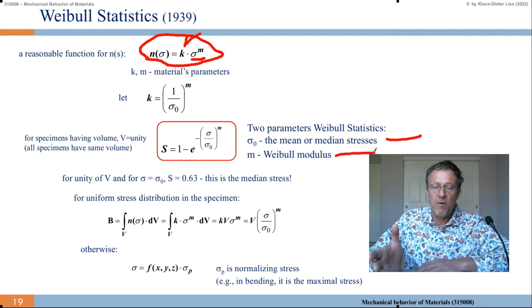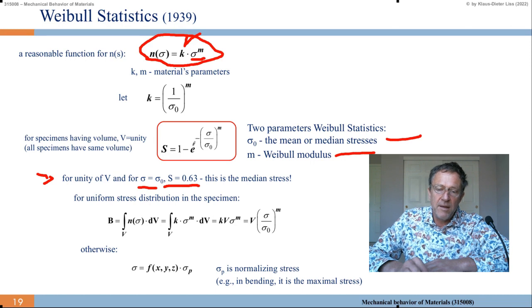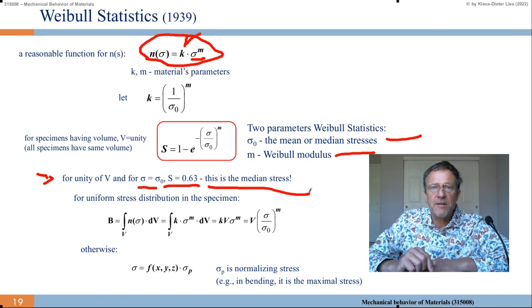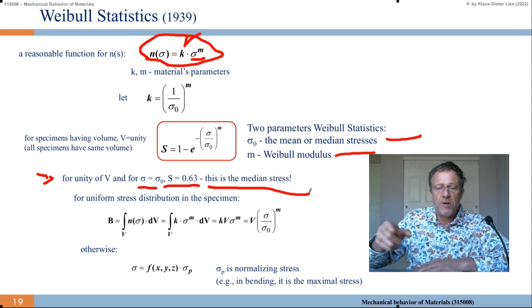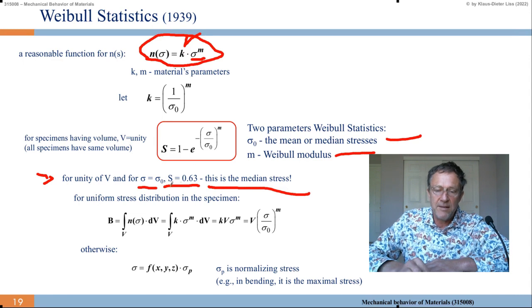We have seen that before, right? For unity volume and sigma equals sigma 0, then that becomes 1, e to the minus 1 to the m is e to the minus 1. 1 minus e to the minus 1 is 0.63. So this is the median stress. And in the curves which I've calculated already, you see at 1 they all cross at 0.63 or 63%.